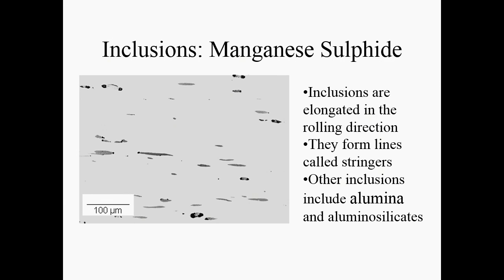This is a particularly bad steel, by the way. If I saw that amount of inclusions in the steel, I'd be saying reject, reject. In fact, this is a steel from the 1960s. So that shows you where we started, really, with all these cases. If you see one inclusion in the field of view in a microscope at 400 times, that's probably okay. 50 is definitely bad.